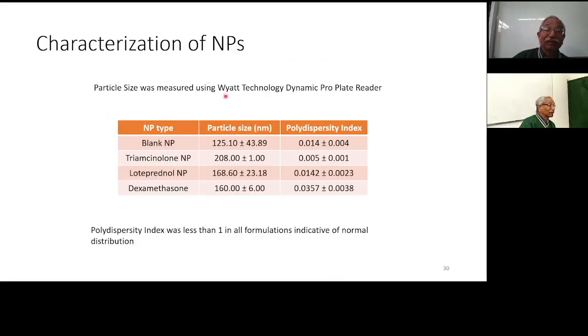So we prepared our nanoparticles, and our blank nanoparticle size was around 125 nanometers. When we added triamcinolone, it became 208 nanometers. We added loteprednol, it became 168 nanometers, and dexamethasone. So all our nanoparticles were around or less than 200 nanometers, and that is the advantage. And then the polydispersity index: when your particle size is compact, the polydispersity index is lower. If it is less than 0.1, then you are very good. So our polydispersity index for the blank was 0.014, which is very low. And then we had 0.005, 0.0142, 0.035.